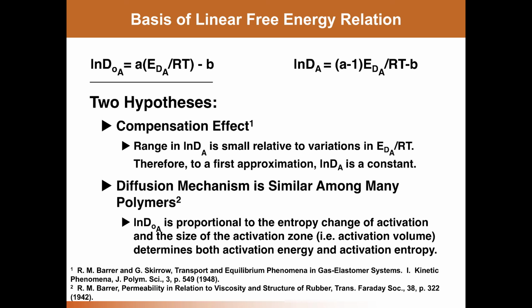And so the diffusion coefficient range that we often probe as a function of temperature is not that great, and any uncertainty in that can then cause this tilting of the line that's fitting the diffusion coefficient data versus 1 over T, and give rise to highly correlated behavior between the front factor D0 and the activation energy ED.